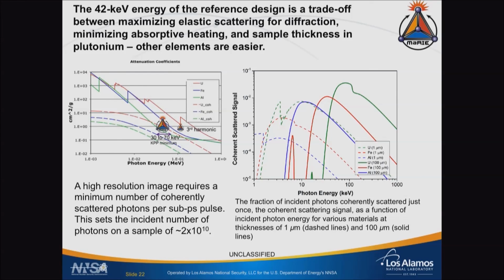And if you work your way out of the box, experimentalists have this term for basically, what's the experimental box I'm in? You have these walls of, I can't go higher than this in energy, I can't go faster than this in time. What can I do to live within the box to maximize my experiments? But if you define the box so that you can actually get away with not thousands of X-ray pulses without heating it up, but maybe tens of pulses, you could maybe make 30 frames of a movie of a mesoscale polycrystalline material during a shock event.